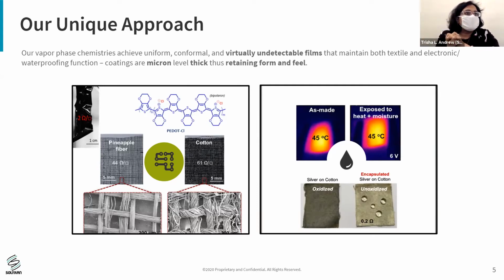Here, the main advantage is that we can actually put down nanoscale thicknesses of the polymers, 500 nanometers all the way up to a couple microns. And that allows you to preserve the underlying properties of not only the substrate, but an underlying coating that you, for example, put the encapsulation on top of. And so, for instance, we could take metallized fabrics and put a nanoscale coating down about 500 nanometers and still maintain the surface conductivity of the silver, which you absolutely cannot do with any other kind of protective layers that you could put down. Next slide, please.